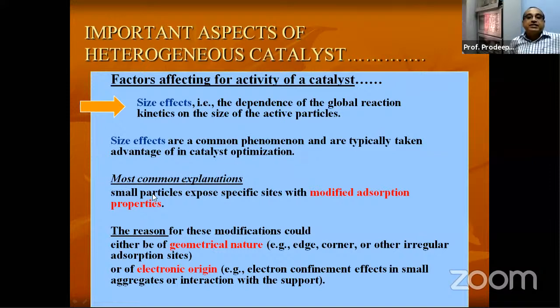The most common explanation is that small particles expose specific sites which are catalytically active with modified adsorption properties. So always, when we carry out catalytic reactions, you will go for adsorption through these catalytically active metals. That is why it is very important. The reason for these modifications could be geometrical in nature, such as corners or other irregular adsorption sites where the catalytically active metals are situated, or of electronic origin, for example electron confinement effects in small aggregates and interaction with the support. So these are typical phenomena used to explain the catalytic activity of a particular heterogeneous material.